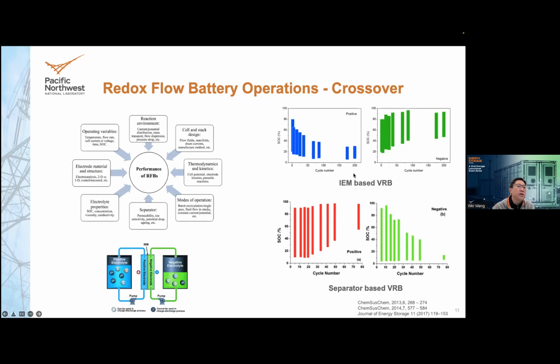So the upper one is showing a IEM-based redox flow battery. Looking at the SOC change during cycling, you can see the positive side SOC shrinking, going down, while the negative side is going up. But if you have a separator-based flow battery, they actually go in the opposite direction. The positive side will go up while the negative side goes down. So those crossovers have to be examined through the different driving crossover mechanisms. For example, in the IEM-based one, diffusion is a major driving force, while in the separator-based flow batteries, convection is a major driving force. So those all have to be considered.